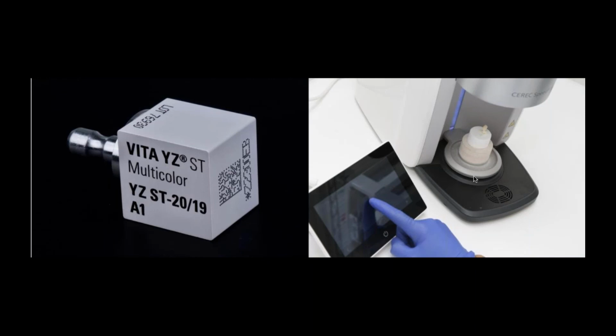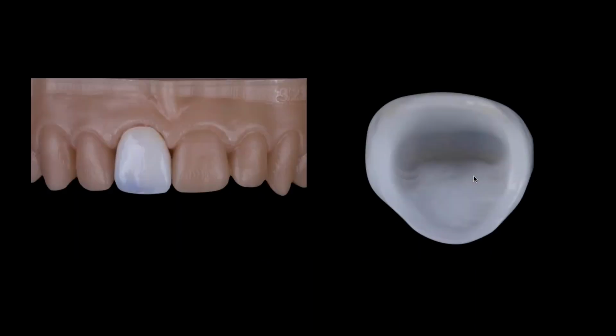So this material has 4% of yttria and can be speed sintered without affecting the final translucency and the final color when we mill it dry. So my recommendation also would be to mill it dry, and you don't need to go through the drying cycle. You can go directly to the speed sintering, making the workflow very attractive.